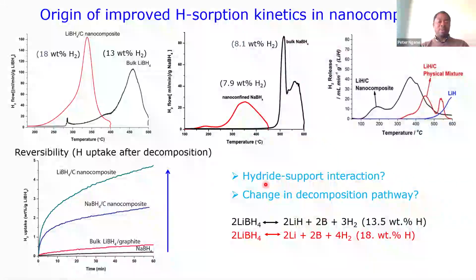Why do we talk about a change in the decomposition pathway, which is actually changing the thermodynamics? Because if we heat bulk lithium borohydride, it goes into lithium hydride plus boron and hydrogen, and this reaction will give you about 13.58% hydrogen. However, if you put this lithium borohydride inside these small nanopores, as you can see here, this is a one-step decomposition. And this one-step decomposition gives rise to 18 weight percent hydrogen, which means that we have straight decomposition of this material into metallic lithium, boron, and hydrogen.